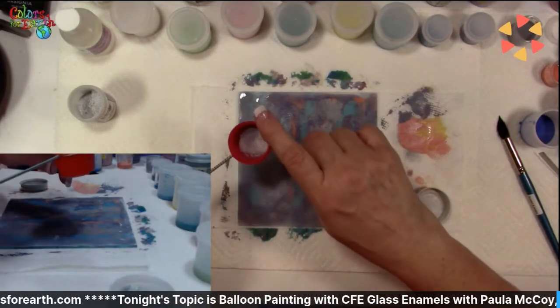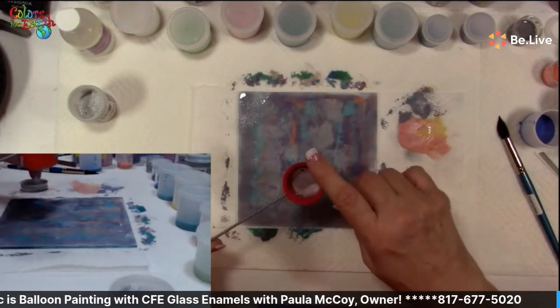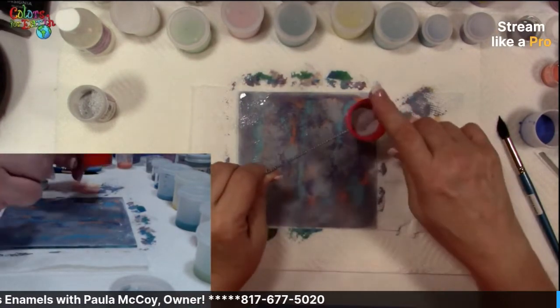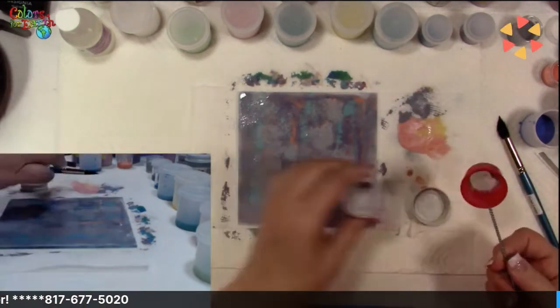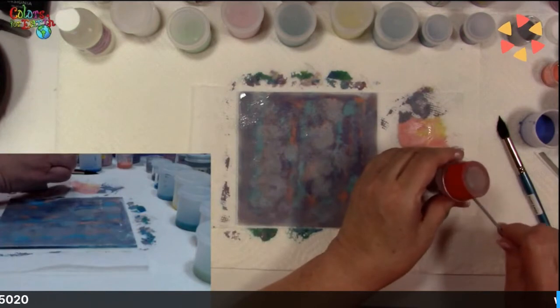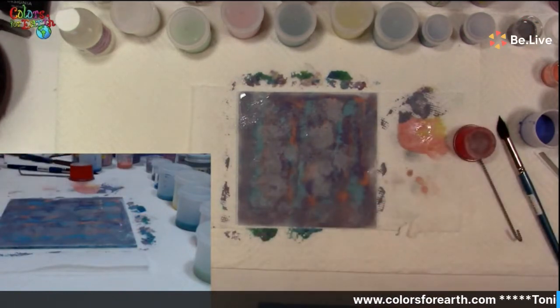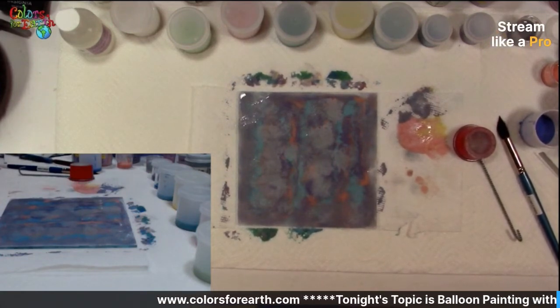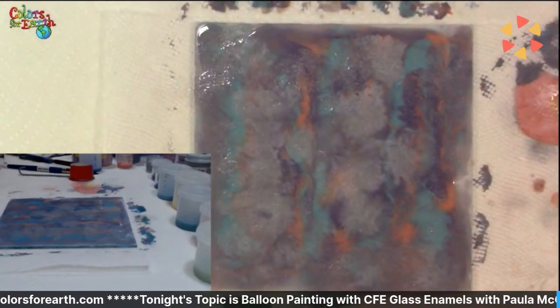What happens if you add a glass frit, such as with a silver color, when it's used flat? So the question was, if they added a frit that was a color, whatever that color might be, would it fuse flat? Absolutely, because if you're going to a full fuse, yes. If you're not, remember, you've got to go to a minimum of 1380. Okay, I'm going to zoom in again so you can see that.